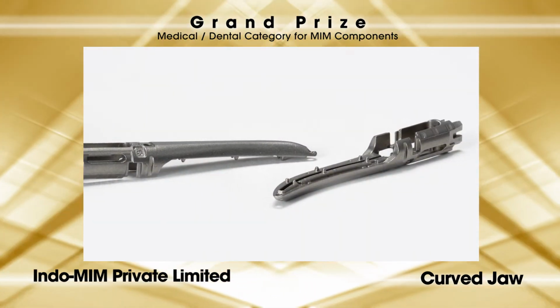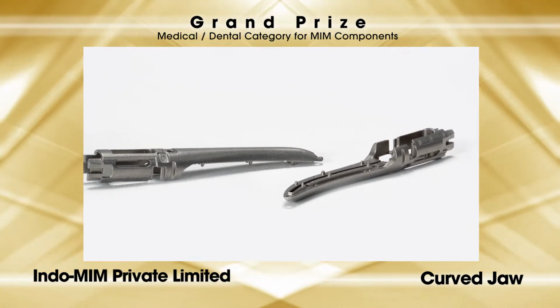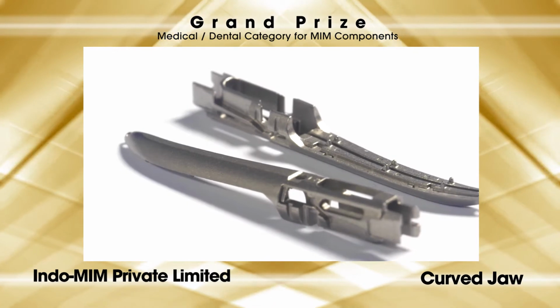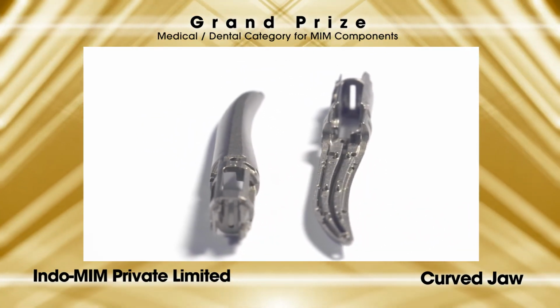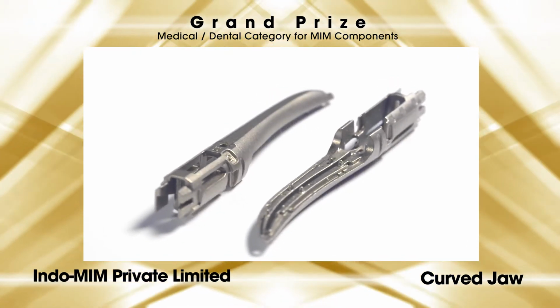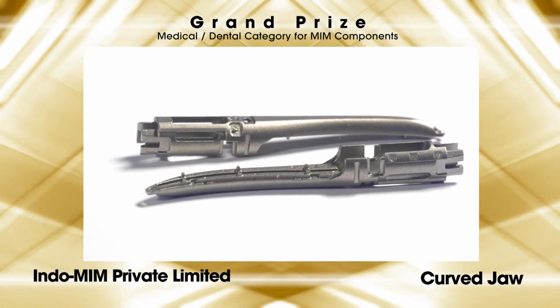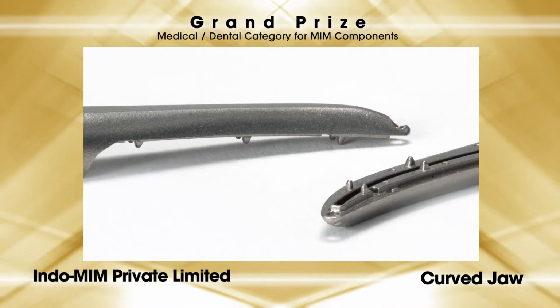Designed for MIM, molding this component without defects was a challenge due to the thin wall thickness in a few areas and obstructions to material flow associated with the complex part design. Preventing short fill in the 6 miniature blind bumps was difficult since no localized inserts and air vents could be used in this area. Innovative tooling design and special mold heaters were utilized to ensure uniform filling of this part with its multiple complex features and blind spots.